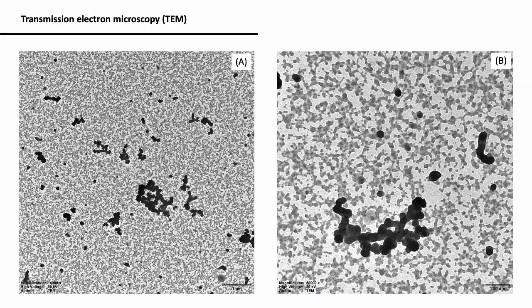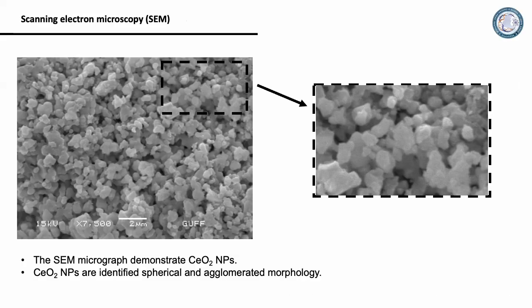The morphology of cerium oxide nanoparticles was characterized by TEM and SEM evaluations. TEM results revealed a uniform and spherical shape of cerium oxide nanoparticles. The TEM micrograph also demonstrated appropriate distribution of cerium oxide nanoparticles with around 30 nanometer diameter under ultrasonic agitation. This result correlated with the crystallite size calculated using the Debye-Scherrer formula. SEM results showed the obtained spherical morphology in the nanoscale range with agglomeration.